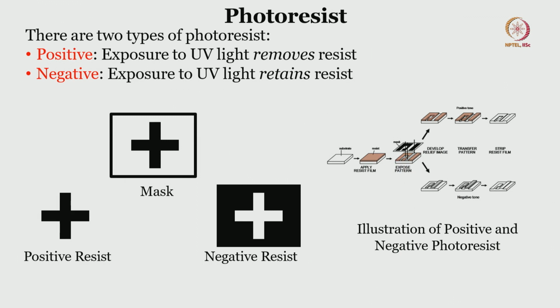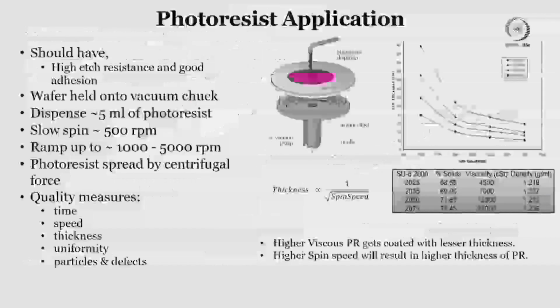And again, this is what I have shown you in terms of how the bright field mask looks like, how the dark field mask looks like, and how the different masks will create different kinds of patterns depending on what kind of photoresist you are going to use. This is a very simple example where it shows that if you have a bright field mask like this, and if you go for positive photoresist, you can regain the same pattern. You see, this pattern is the same as your mask. This is the mask and the pattern, let us say we call it P, then we have the same pattern P here when we go for positive photoresist. With negative photoresist, we have P inverse or P star, which is the inverse pattern of whatever there is on the mask. So, wherever there is a bright area, it becomes black, and the black area becomes bright, right. So, dark or bright in those terms. So, negative photoresist, positive photoresist, the use of it when we use bright field mask and dark field mask.